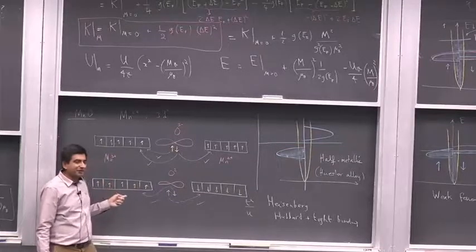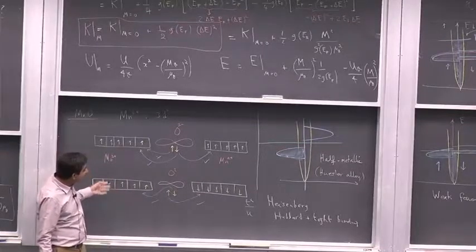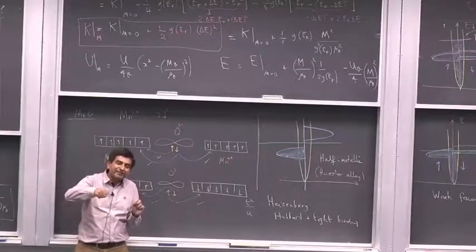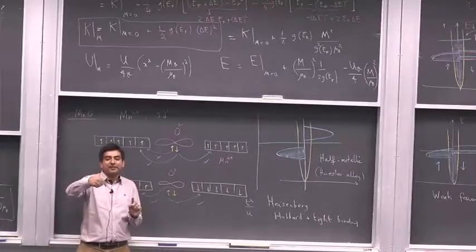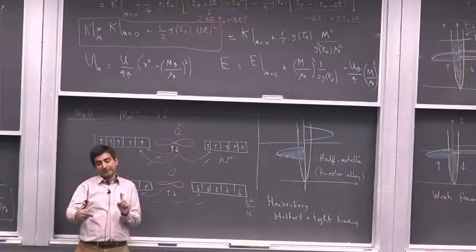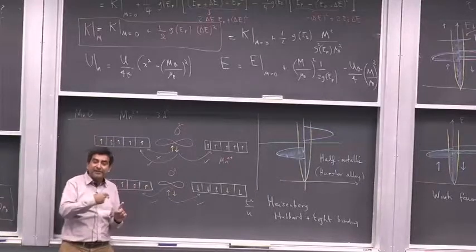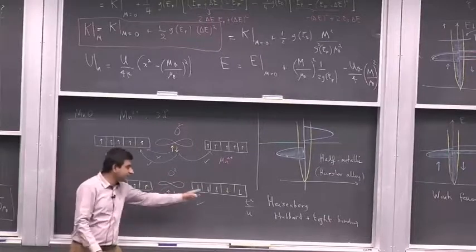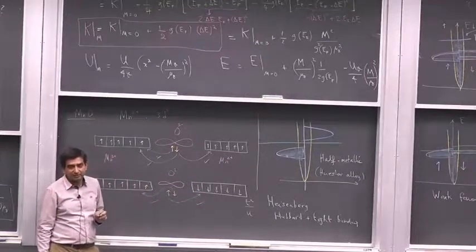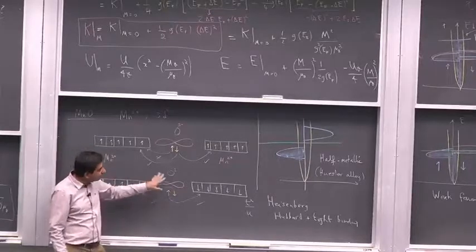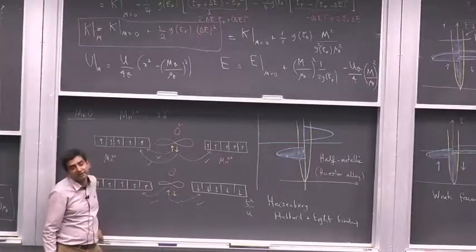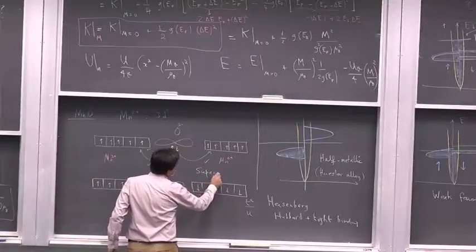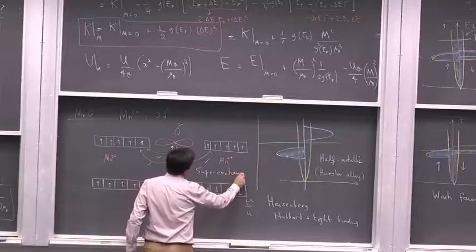So this configuration necessitates that two neighboring manganese ions have their spins pointing in opposite directions. This is how anti-ferromagnetism is energetically favorable for manganese oxide. This is why this insulating oxide is anti-ferromagnetic, and there is no direct exchange interaction between these ions. This kind of interaction is called a superexchange interaction. It's an example of a superexchange interaction.